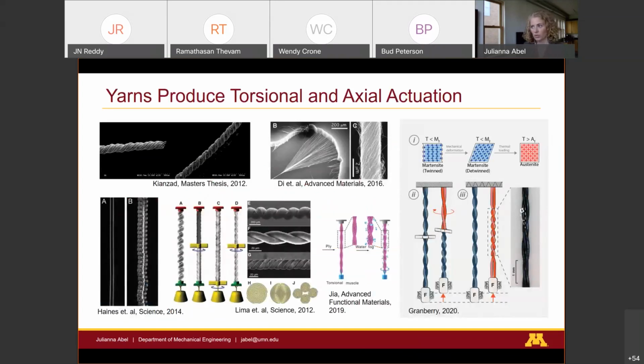So yarns produce torsional and axial actuations. There's been a lot of work on this recently, using different material systems, shape memory alloys, shape memory polymers, carbon nanotubes, and different yarn architectures. And they all typically use either thermal expansion or some type of swelling effect in order to provide linear and torsional actuation. And so we're looking at how do we enable this with shape memory alloys, because right now, if you look at what's commercially available, they're pretty large diameter wires, and so it's hard to make a yarn out of diameters on that scale without causing permanent deformation.